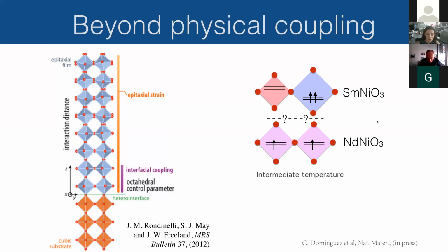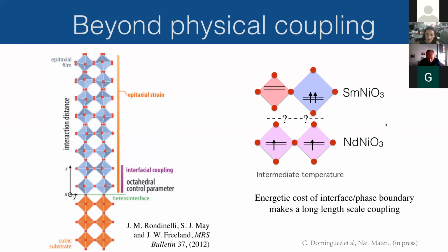And then it turns out, and we used a Landau model to find this, that there is actually a very high energy cost of having an interface between these two materials at a given temperature, because that represents a phase boundary between this very disproportionate insulating state and this very proportionate metallic state. And this is what is setting the long length scale coupling of the system.